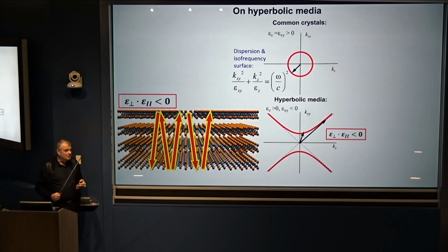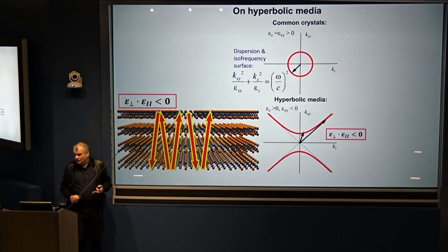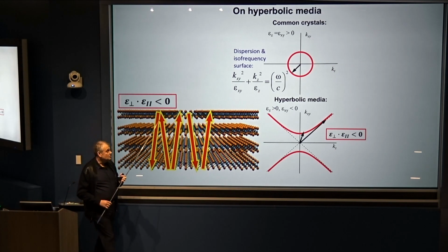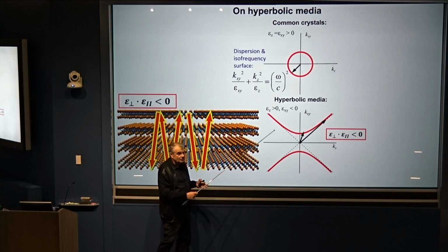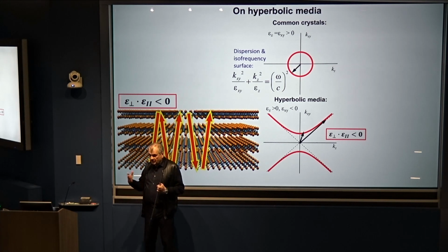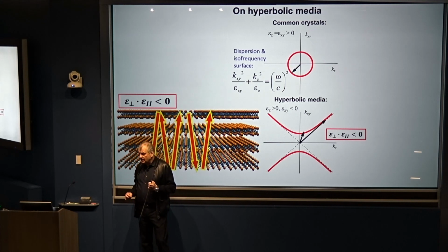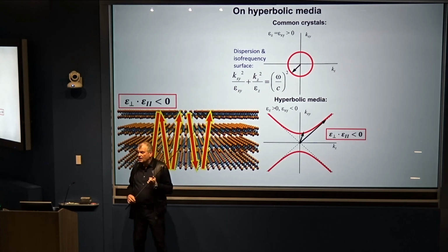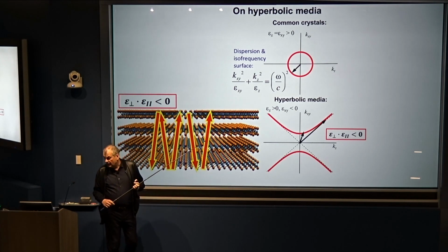Anything infinite in materials is a rare occurrence, and certainly in hyperbolic media, that's what you get. Because you have such high wave vectors, the spatial resolution of imaging in hyperbolic material becomes limited by interatomic spacing. Optics and interatomic spaces do not often come in the same sentence, and that's what hyperbolic media again delivers.